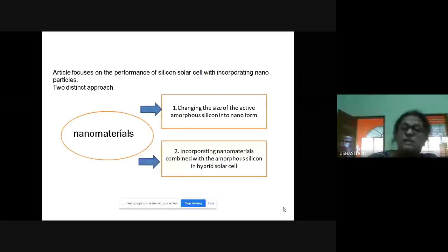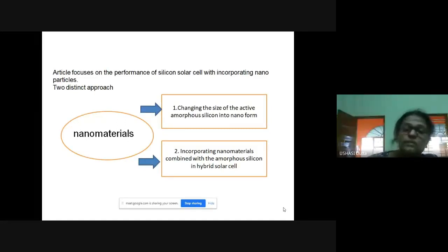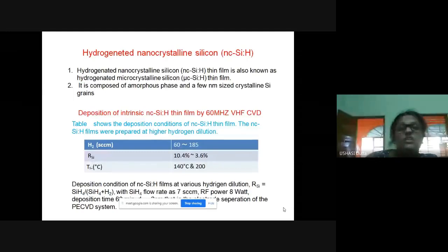My article focuses on the performance of silicon solar cells incorporating nanoparticles. We use two distinct approaches: either changing the size of the active amorphous silicon into nano formation, or incorporating nanomaterial combined with the amorphous silicon in a hybrid solar cell. The hydrogenated nanocrystalline silicon, actually called hydrogenated microcrystalline silicon thin film, is composed of an amorphous phase with a few nanometer-size crystalline silicon grains embedded in it. This is the deposition table showing how nanocrystalline silicon hydrogenated films were prepared by changing to higher hydrogen dilution.